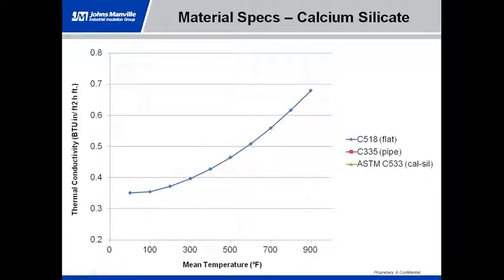So to start off with, we talk about material specs, and in this case we have calcium silicate. ASTM has a standard specification for all insulation material types. They have them for calcium silicate, perlite, mineral wool, microporous, and silica aerogel products. Now, looking at this set of data, we have ASTM C518, which is flat testing, and we develop a thermal curve. And how we do this, again, we started at a set point at 100 degrees. So we have a hot plate, a cold plate. We wait for everything to come to equilibrium.